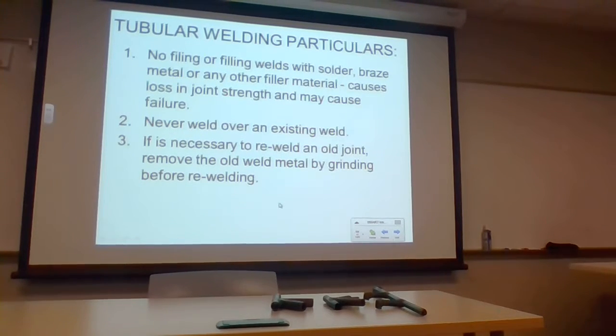No filing or filling of welds with solder, brazed metal, or any other filler material. That causes loss of joint strength. The temptation is always there to try to make something look better cosmetically, but in essence, what you're doing is really weakening the joint by trying to braze over on top of it or fill in nasty-looking welds that don't actually fare into the metal very well.